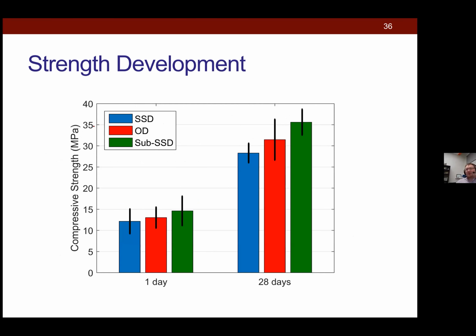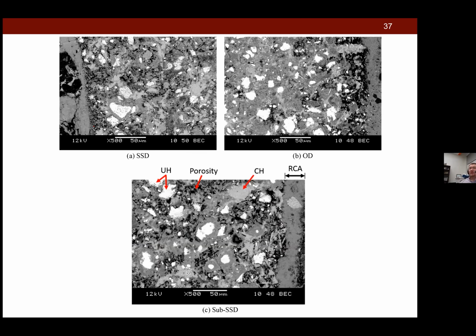We basically took a 0.42 water cement ratio cement paste, right? And we didn't change the moisture there. Then we took RCA that's saturated, oven dry, or like 80% SSD, and mixed that as is into the paste. So yes, I know that that's sacrilegious. We're not accounting for the moisture content there, but that's what we were trying to study. We're trying to figure out what happens if you mix an oven dry RCA that wants to absorb 7% moisture. What's it going to do to your local water cement ratio? The answer is it's probably going to screw things up quite a bit.